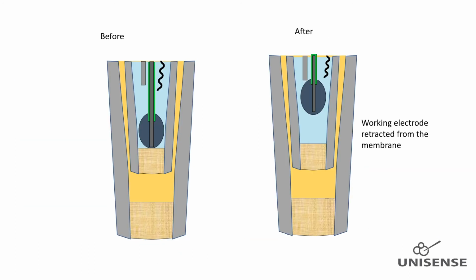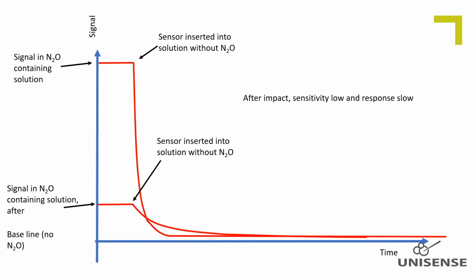If a sensor experiences a physical impact, like a drop on the table, the working electrode could be displaced. If the displacement results in a working electrode retraction from the silicone membrane, the signal will be slow and sensitivity low. The sensor will still work, but it will have lost its original behavior. It is unfortunately not possible to restore original performance after such an event.